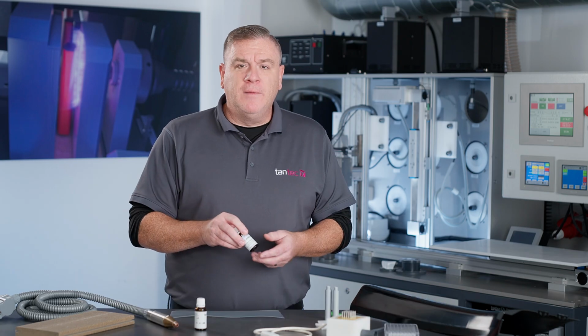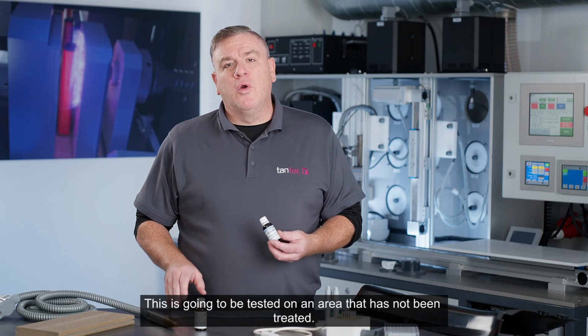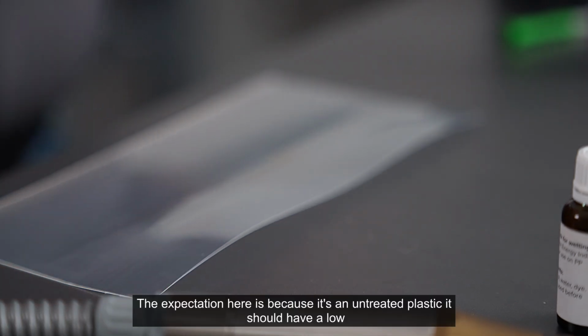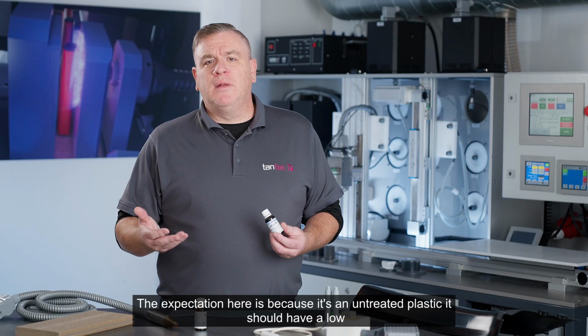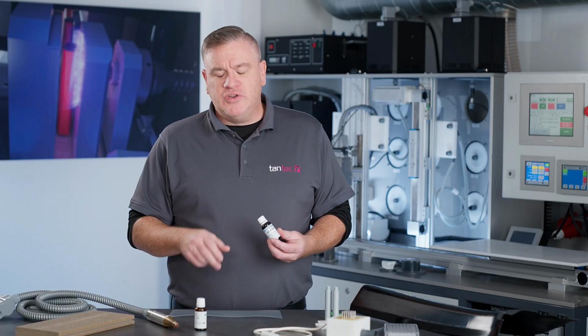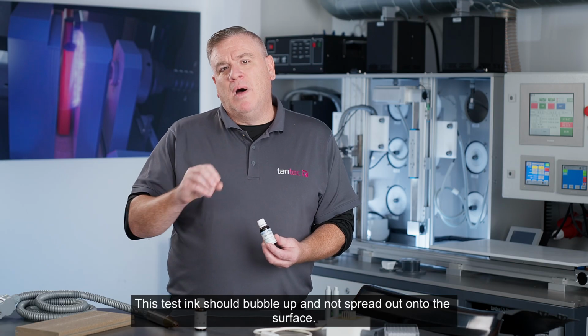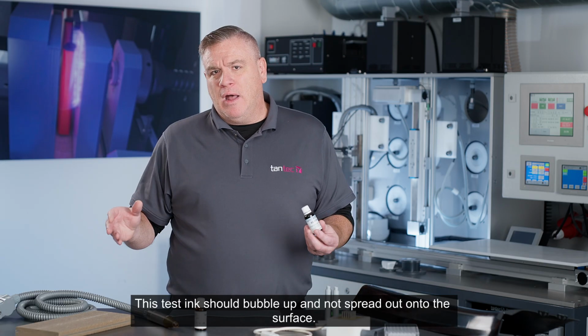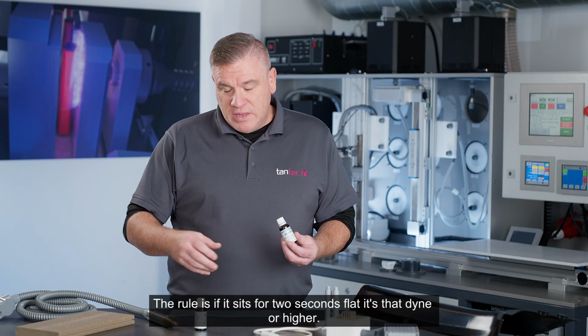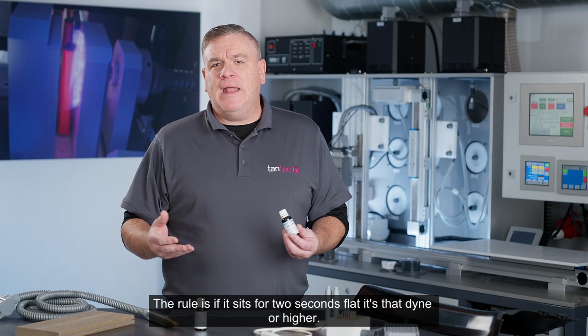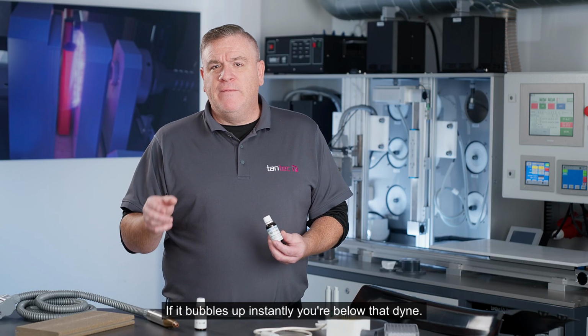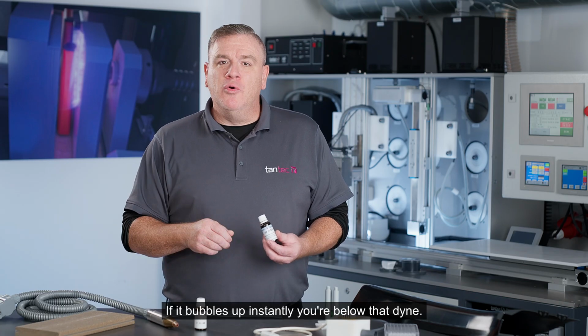So the first test we're going to do is with a lower number, which is a 40. This is going to be tested on an area that has not been treated. The expectation here is because it's an untreated plastic, it should have a low surface energy. This test ink should bubble up and not spread out onto the surface. The rule is if it sits for 2 seconds flat, it's that dyne or higher. If it bubbles up instantly, you're below that dyne.